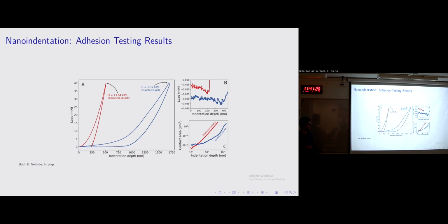And you can see, in the close-up of this region in this frame, that there's a minimum, and we're in negative load. So we actually have to pull on the nanoindenter tip to start detaching it. I told you that we know the contact area as a function of the indentation depth for different materials. This is a log scale, and I've done this a bunch of times with different geometries and different substrates to get a general trend.